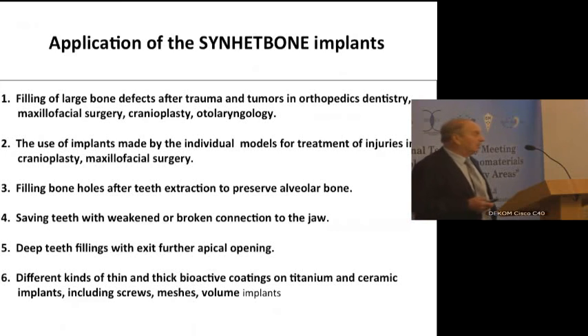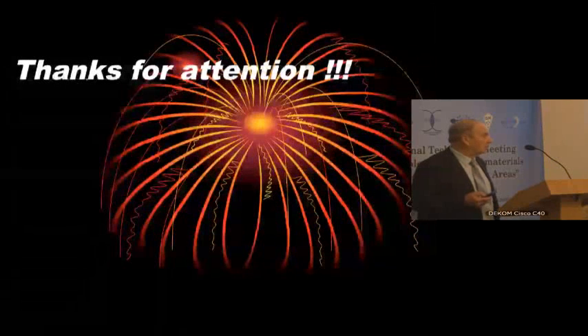So we achieved the result, and after 6, 8, or 10 months, we managed to produce the real layered bone tissue, but also to restore the bone marrow. This result has never been achieved before. So the further development of these materials allowed to guarantee full biotransformation after a year. Transformation to the real bone, not only the primary period of raw fiber bone, but to fully restore even the bone marrow, which is, of course, very necessary for the body.